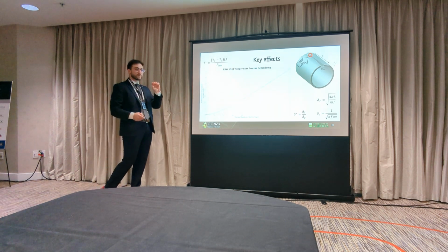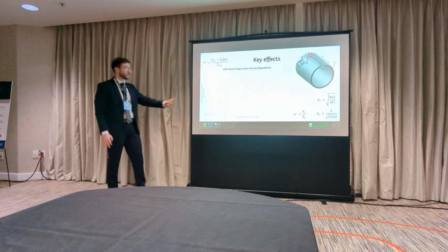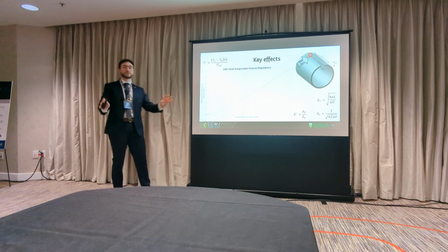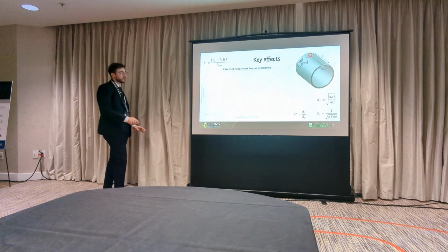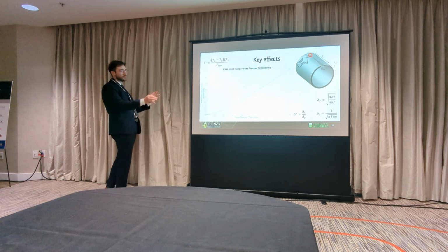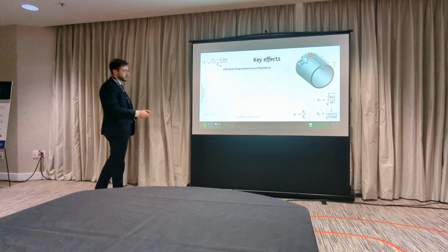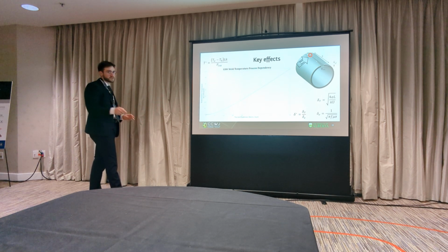Now, in terms of for an operator, this curve means nothing. Numbers mean nothing. What it means for the engineer is the shape of the curve is important. If you zoom in and you look at the curves really closely, you'll see that it behaves in two asymptotic ways. One is, as your delta star, your thermal depth, gets really large, the curve behaves asymptotically linear. And as you go really small, the curve is more curved, and it's asymptotic as your delta E gets really large, as this ratio gets small.